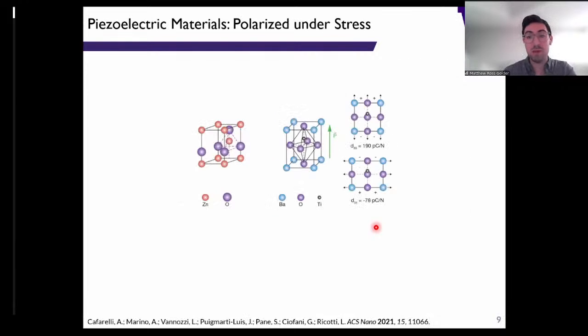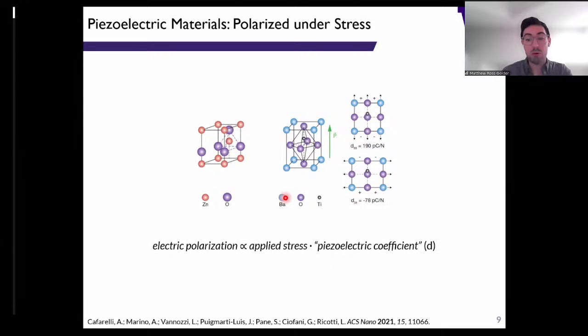So these piezoelectric materials I alluded to on the previous slide are these metal oxides that become polarized under stress. And that's because they have this non-centrosymmetric lattice structure. So in this case, we have zinc oxide on the left and barium titanate on the right. And the way that we can think about this is the electric polarization of this material is going to be proportional to the applied stress and some type of piezoelectric coefficient that we're going to term d.